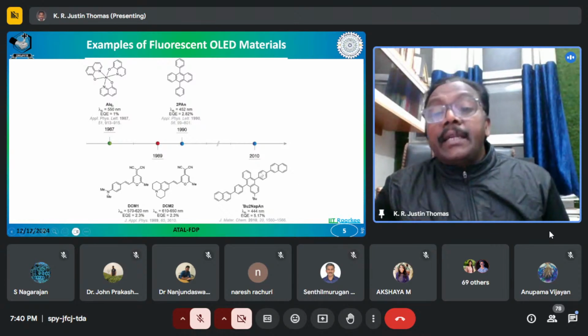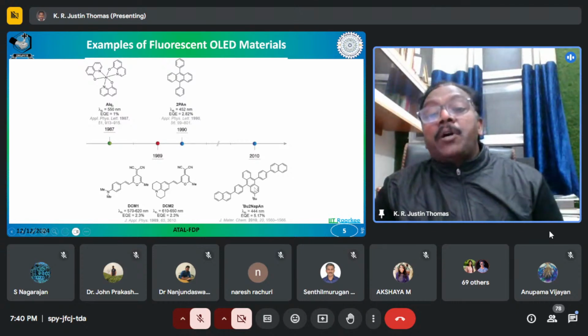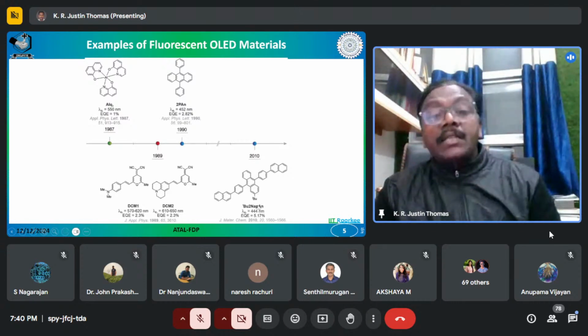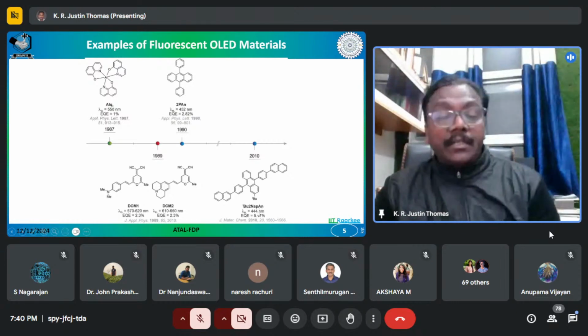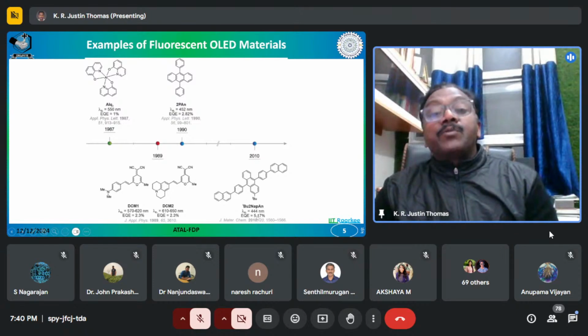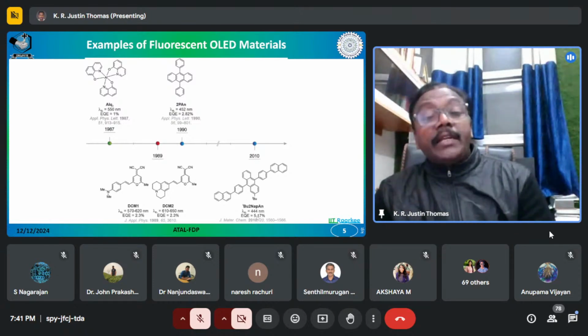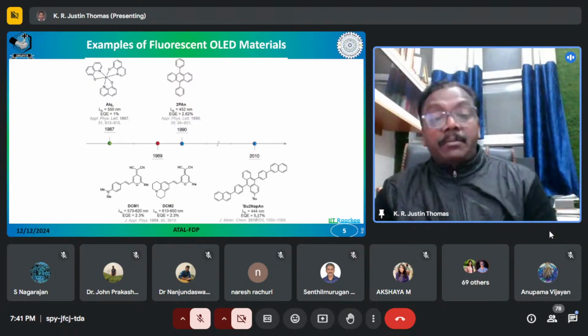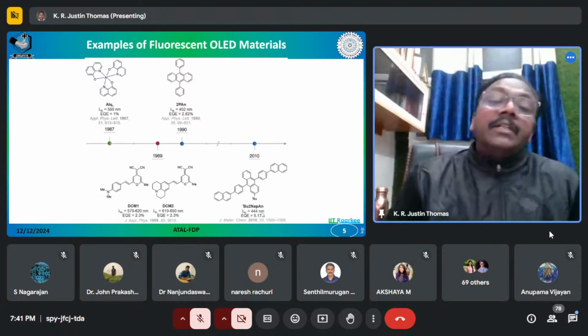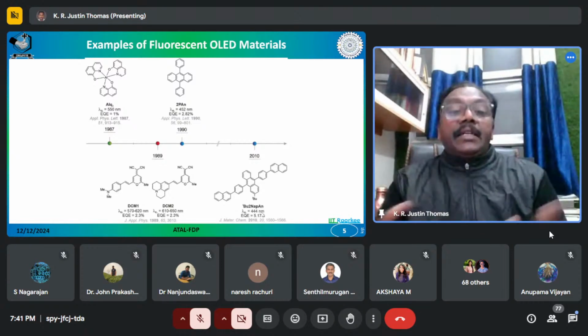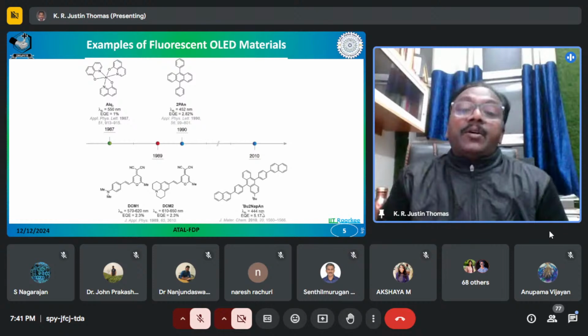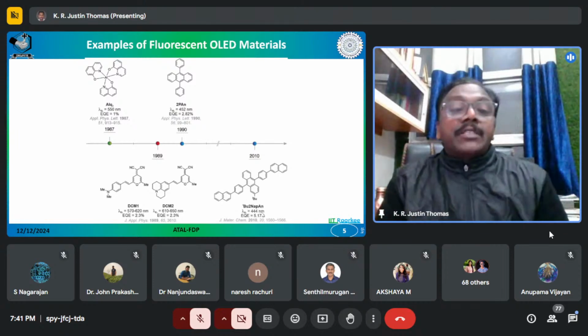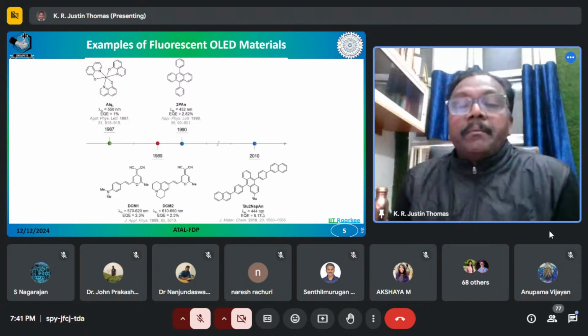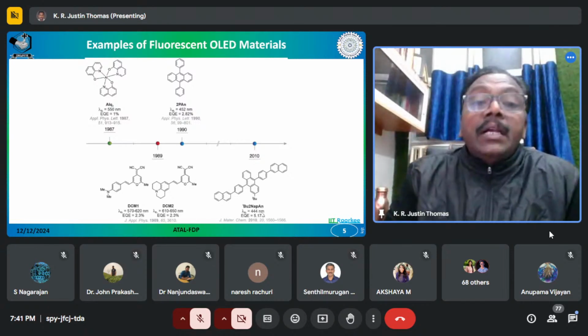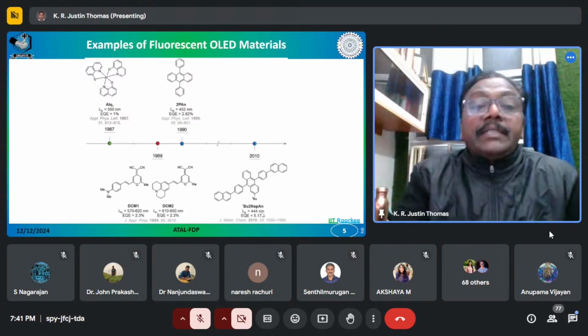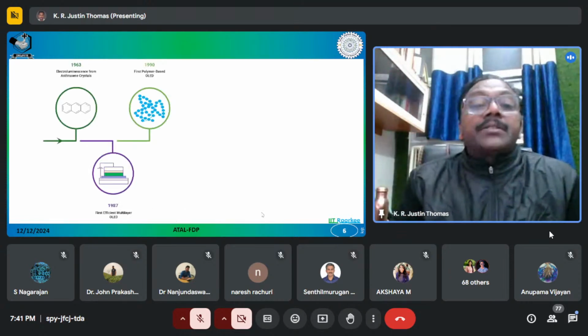And then in 2010, there was an anthracene-based molecule which has shown efficiency crossing the theoretical limit of 5%. So that is an interesting breakthrough. So what is the reason for that? I will be addressing this molecule later on, but this is not a normal fluorescent material. That is an important aspect about this molecule. This is the crossover material. It's called a P-type delayed fluorescence material, which was first observed in fluorescent pyrene. P-type delayed fluorescent molecules. Okay, so I will come to that one later on, but this is the history of fluorescent LED materials.